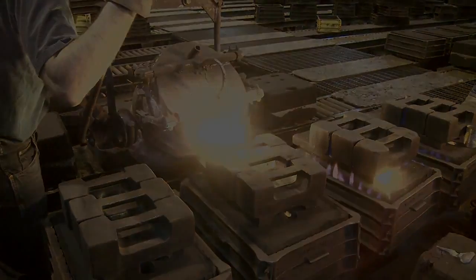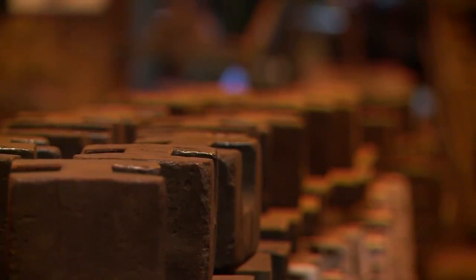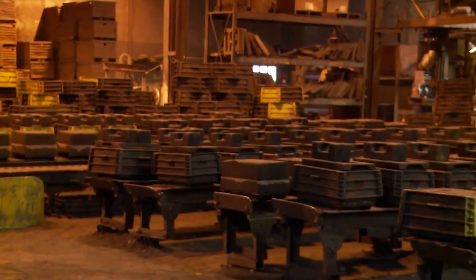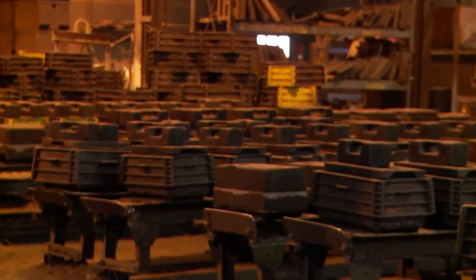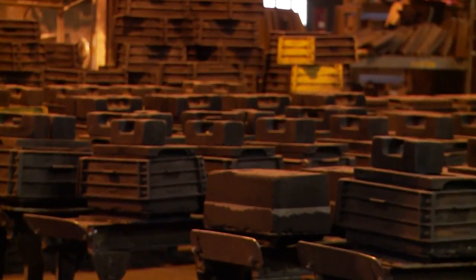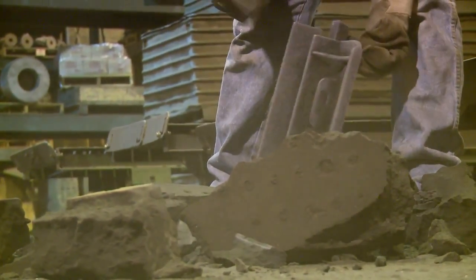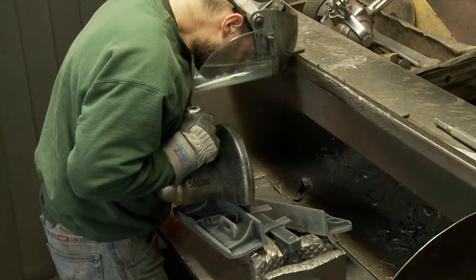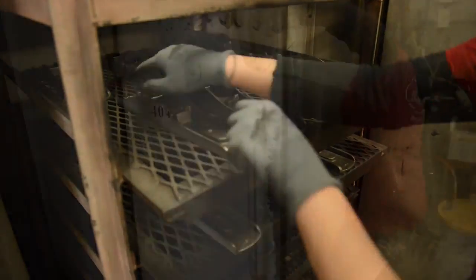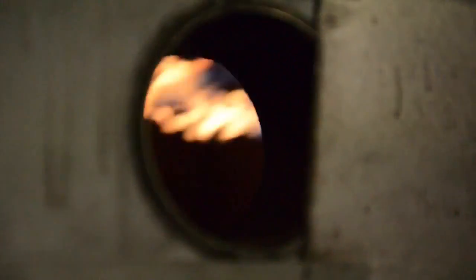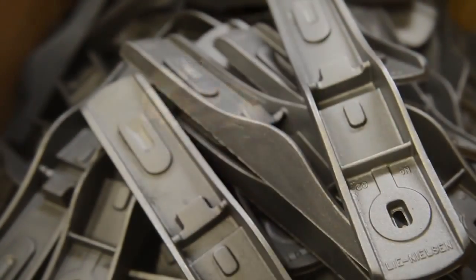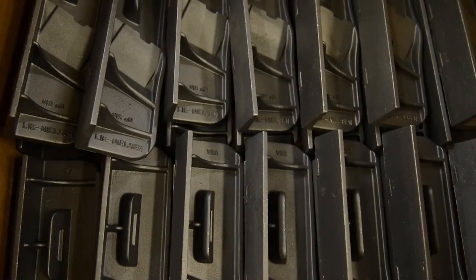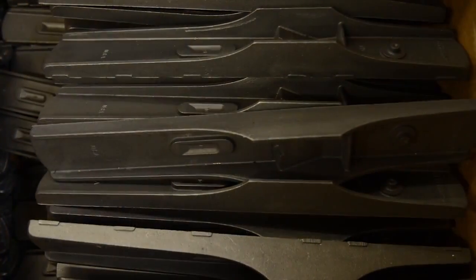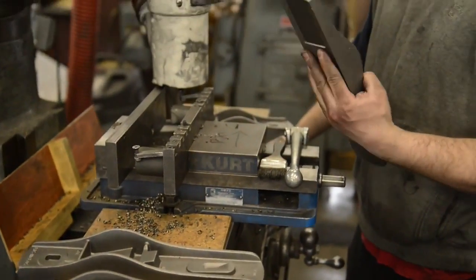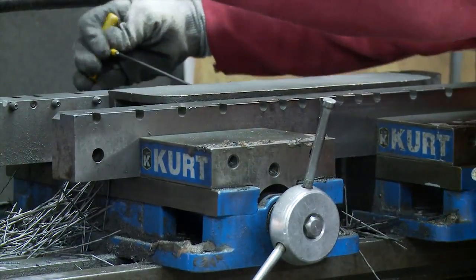In the period when I started making tools, nobody stress relieved anymore. But one of the things I like to do is to leave the casting in the mold overnight so it cools off as slowly as possible. The other thing that we do with all of our castings is to heat treat them or stress relieve them by heat. After they're cut off of the tree, they're put into an oven and heated up to a very hot temperature, and then they're cooled off, and the cooling off slowly is the most important part. So we take a lot of care in this process and have not had problems with castings that don't stay flat because there's stress in them.